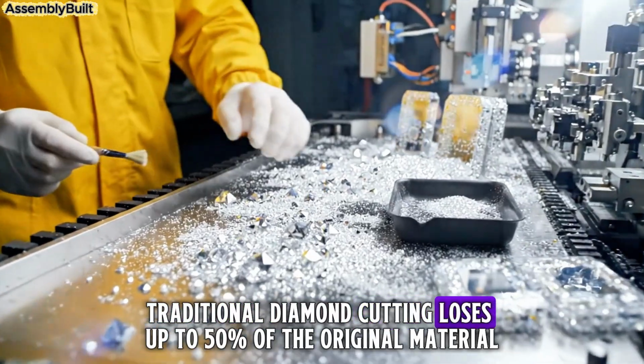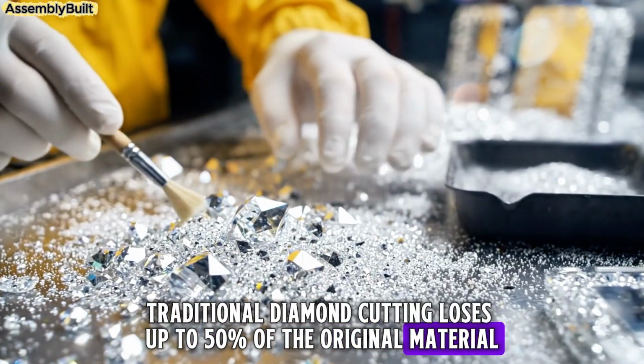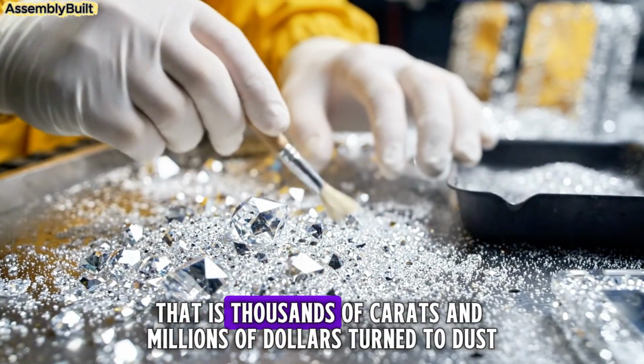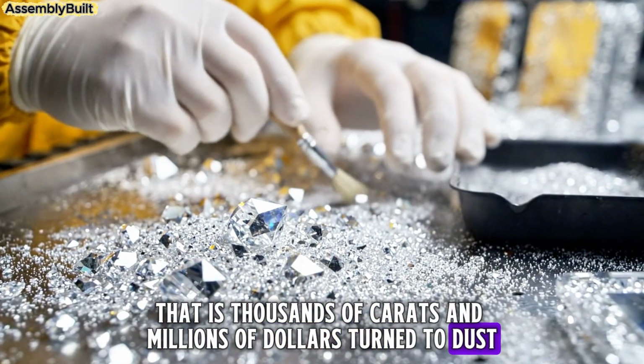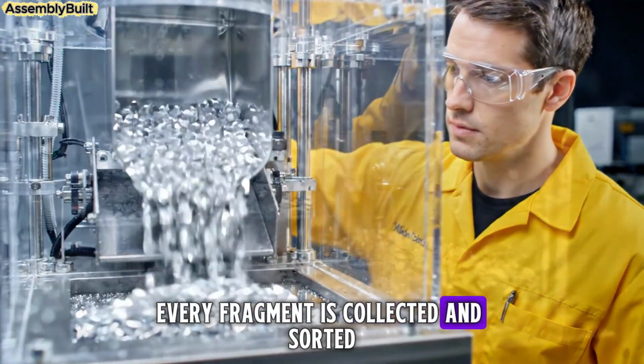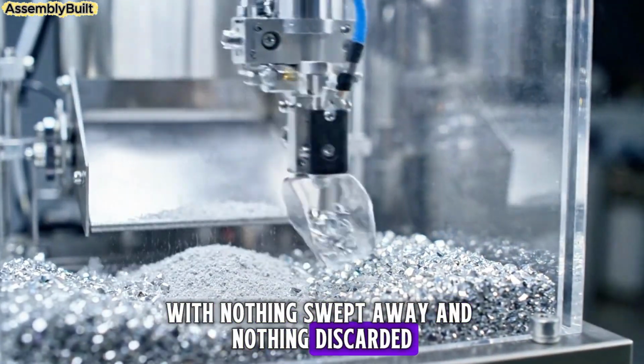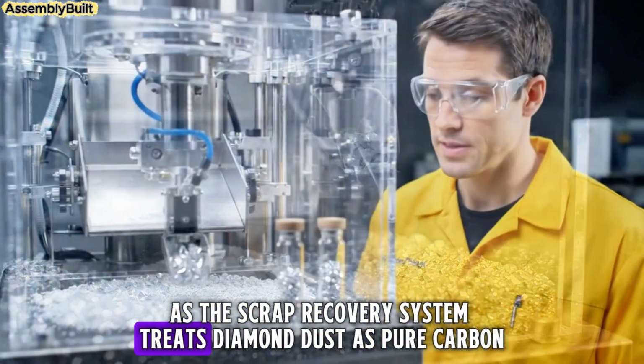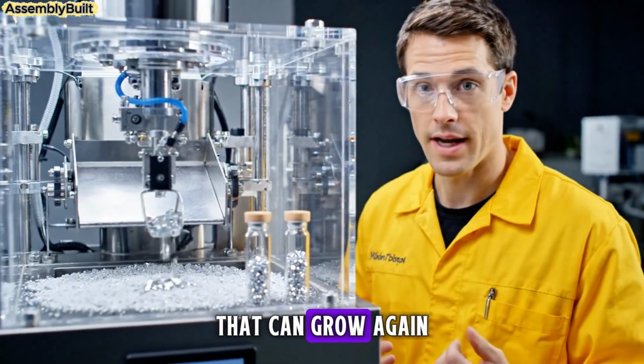Traditional diamond cutting loses up to 50% of the original material, and for 10,000 stones that is thousands of carats and millions of dollars turned to dust. Every fragment is collected and sorted with nothing swept away and nothing discarded, as the scrap recovery system treats diamond dust as pure carbon that can grow again.